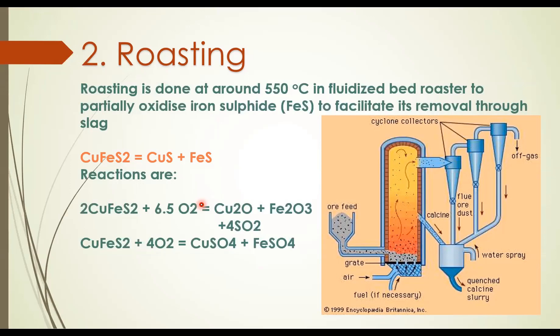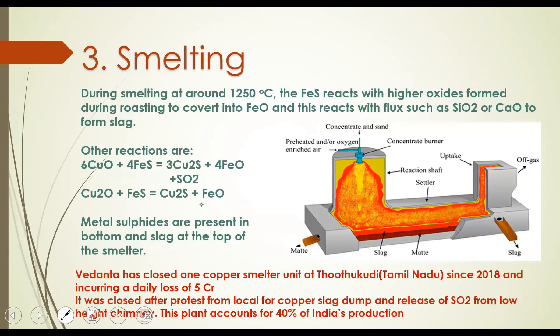Now the next process is matte smelting. The Cu2O formed earlier reacts with the leftover FeS, because FeS oxidation only takes place in a small amount during roasting. We heat at a very high temperature of 1250 degrees centigrade. The combined reaction produces Cu2S, which is called matte — you can see in the furnace the bottom part is the matte. Just above this is the slag, formed from the FeO produced, combined with added SiO2 (silica) to remove FeO.